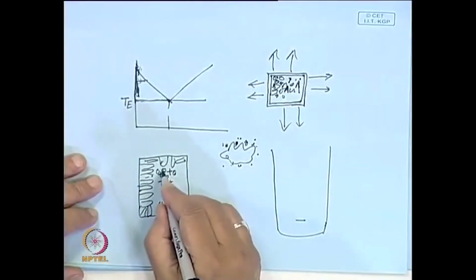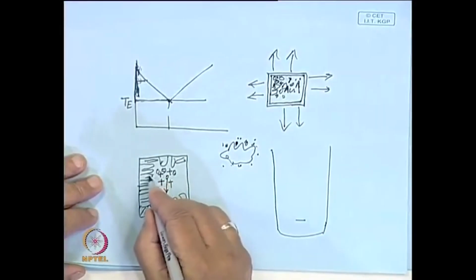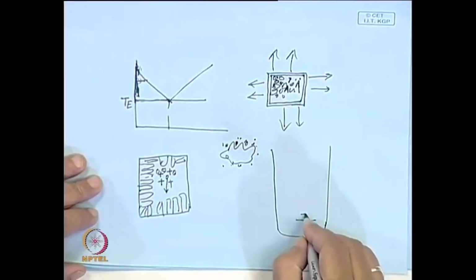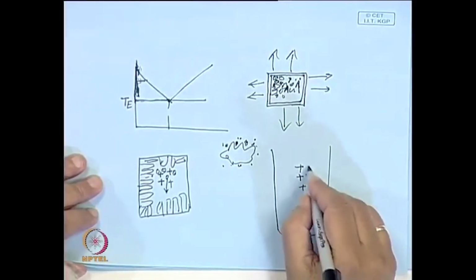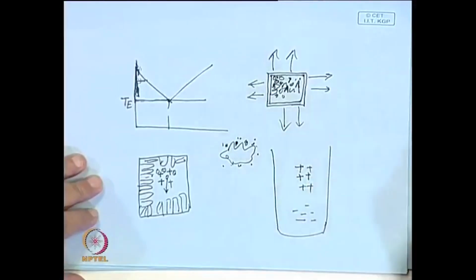The first solid that precipitates out is purer. So you get negative segregation here and positive segregation in these parts, and this segregation you will always get in alloys. One way you can control it is by controlling the processing, the nature and extent of segregation.